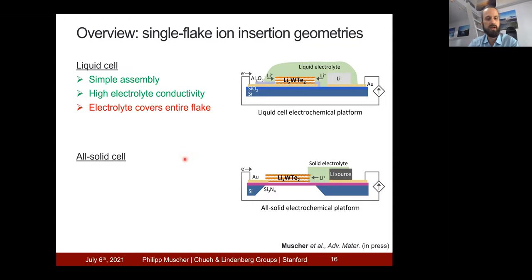So for this purpose, I also built an all-solid cell where we use solid electrolyte instead, which is spatially confined such that most of the flake is not covered by anything. This makes this platform also vacuum compatible. And another thing is that here we can back etch the chip on which the flake is, such that the flake is only sitting on a 50 nanometer thick membrane. So this allows, for example, for laser transmission experiments that are unperturbed.